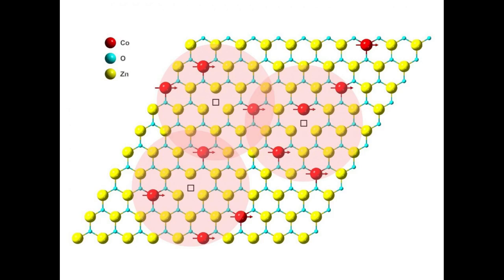As a whole, the research team's lab experiments showed that the graphene zinc oxide system becomes weakly magnetic with a 5 to 6% concentration of cobalt atoms. Increasing the concentration of cobalt atoms to about 12% results in a very strong magnet. To the researchers' surprise, a concentration of cobalt atoms exceeding 15% shifts the 2D magnet into an exotic quantum state of frustration, whereby different magnetic states within the 2D system are in competition with each other.